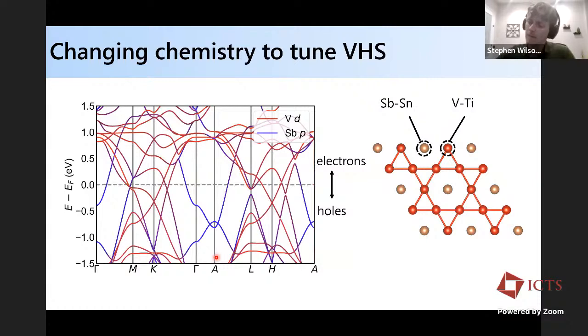Okay, so another thing we can do is we can alloy the system, and we can try and change the filling to try and explore nearby instabilities, okay? And one of the approaches we've done is, we can try and hole dope this system to try and sweep the Van Hove points closest to the Fermi level through the Fermi level, to the extent that we're able to hole dope it. And we can do it two different ways. One is what we regard as the cleanest way: you can replace the antimony site with tin, which is not perturbing the Kagome net directly. And the other is you can replace the vanadium site with titanium, in which case you're putting a substitutional defect directly into the Kagome net.